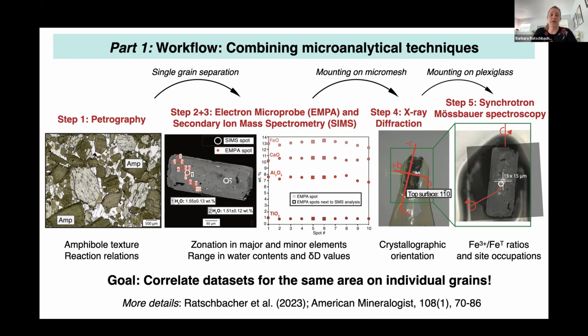We mount them in epoxy and polish them for major element analysis using the electron microprobe. And we also determine the water content in amphiboles and the hydrogen isotope composition. And we do that by using secondary ion mass spectrometry.